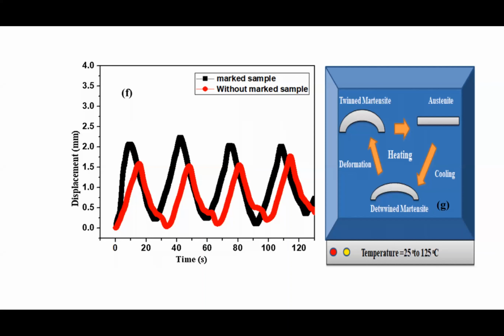As far as this wall thickness is concerned, till now we could go up to 0.25 mm wall thickness. With the 0.25 mm wall thickness, the reliability of our actuator was getting deteriorated, because if you closely observe the mechanism of this shape memory alloy getting actuated, you are doing it in an open environment. There is a switching between the austenite and the martensite, which is nothing but heating. When there is heating, it tries to attract oxide. More amount of oxide will start getting infused into the structure, and at one particular point it will lose its shape memory property.